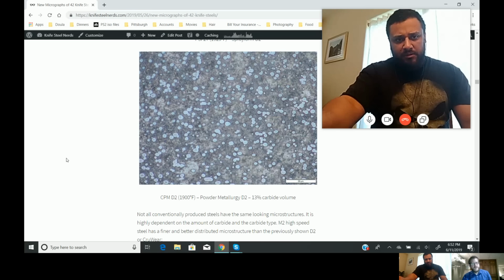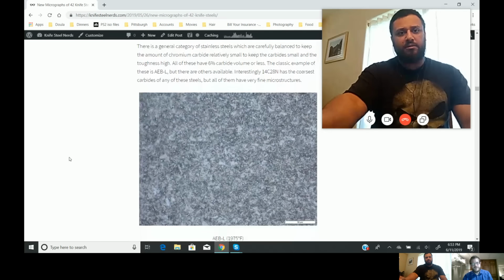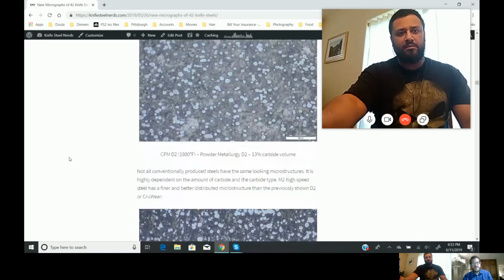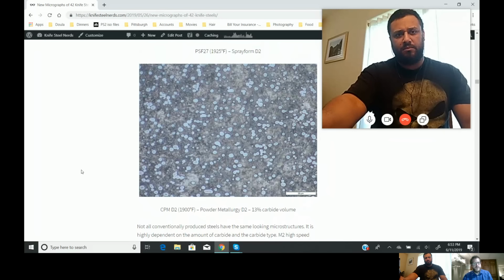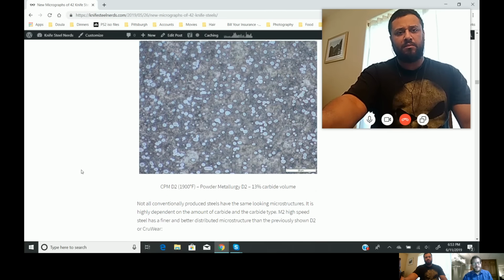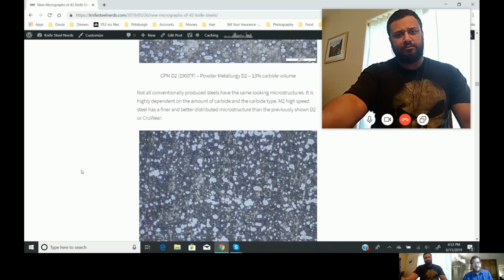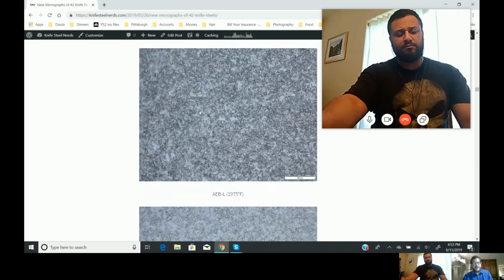Yeah, I don't know if I have a real quick way of explaining the difference between the D2 here and the AEBL. The amount is an obvious one, but because there's more carbide in the D2, the carbides are stable all the way up to melting temperature. So you can't just forge it at high temperature and get rid of the carbides. Those carbides are always going to be there. And if you're not fully getting rid of them, then they're going to get bigger. So it's just impossible to keep them small, really. Where the AEBL, you're forging it at high temperature, they're all gone. And then they re-precipitate as you cool down. And so they're just much smaller due to that fact.